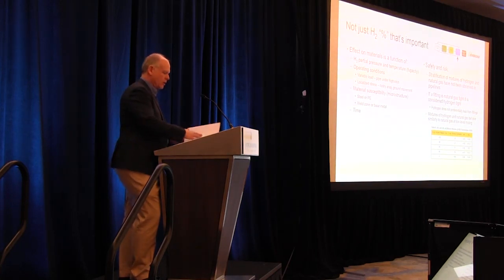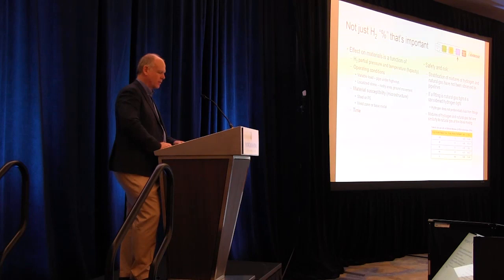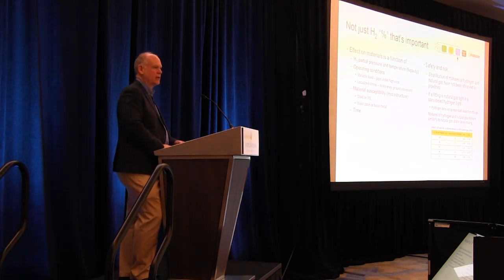And as we were going through our research, we found out it's not just the hydrogen percent that's important. It's a function of the partial pressure and the temperature. It's a function of operating conditions. So variable loads, localized stresses, and I'll talk a little bit about those when I get to the impacts on specific materials. There's microstructure susceptibility issues with steel or plastic. In steel, whether you're in the weld zone or the base metal because of the heat affected zone, and everybody's favorite, father time. How much are we affecting the total lifespan of some of this equipment?